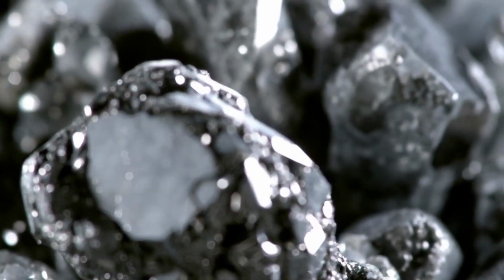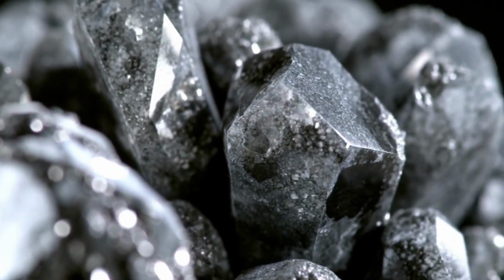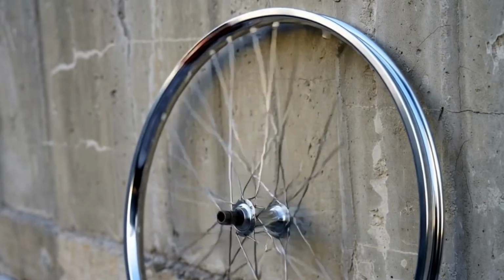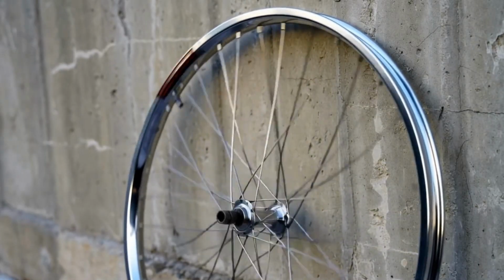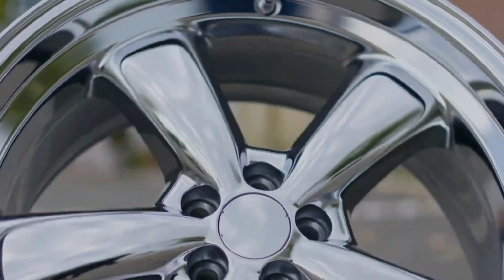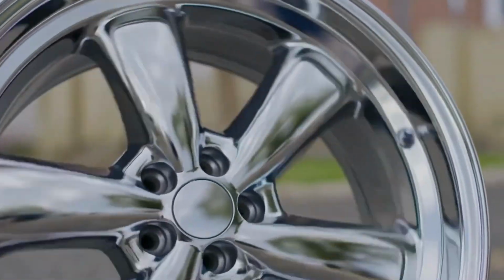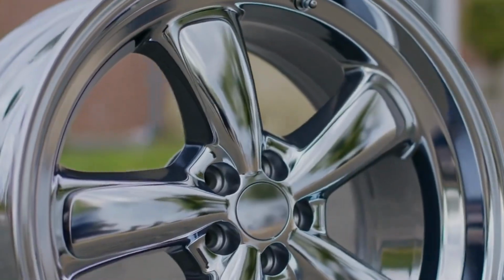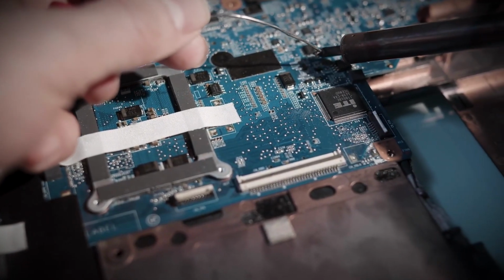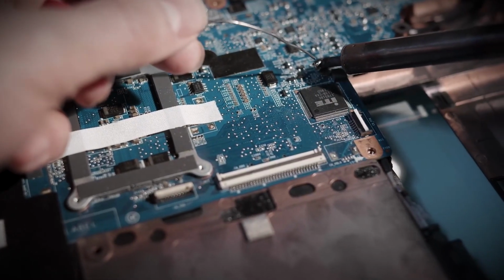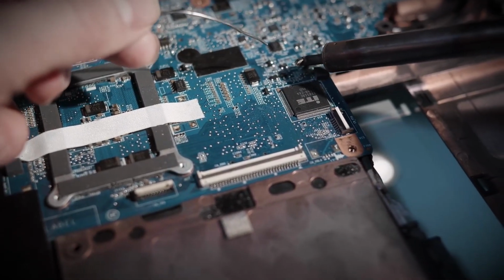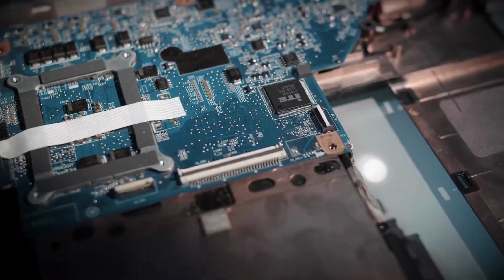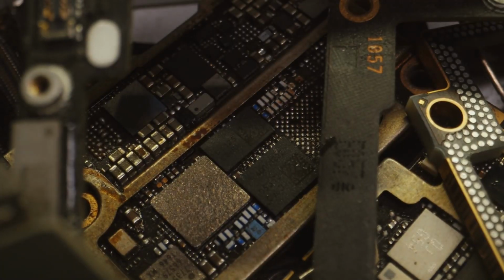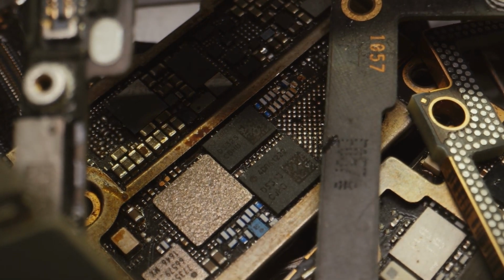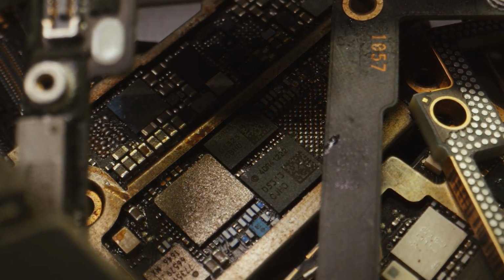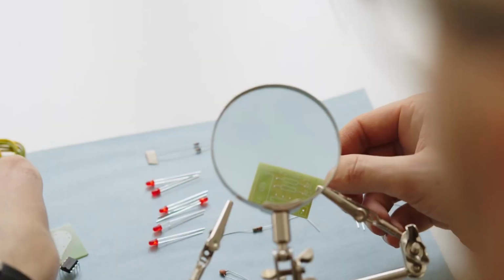Frankly, chromium is one of the most important materials in modern electronics, but almost no one working with computers knows this. Here's how it works. When manufacturing microchips and printed circuit boards, engineers need to deposit metal conductive traces onto the surface of glass, silicon, or a polymer substrate. Copper is a logical choice for a conductor. It is inexpensive, conducts electricity well, and is easy to process. The problem is, copper doesn't stick to glass and silicon. Place a copper film on a glass plate and it will peel off.